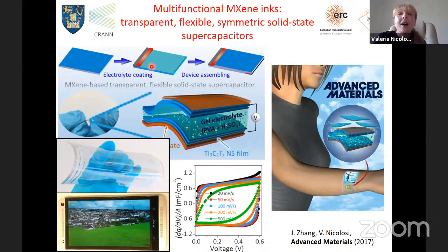substrate with these MXene inks, then coat it with a solid electrolyte, gel electrolyte, and then assemble a second layer of the other electrode all on it. And because these MXenes are so nicely conductive, so good at electrochemistry, and so transparent, we managed to build these very, very large devices. Normally, supercapacitors are tiny, like in centimeters. So it's very, very hard to actually get large devices like this to really work. And what we managed was to assemble a full device of 2 electrodes and electrolytes.